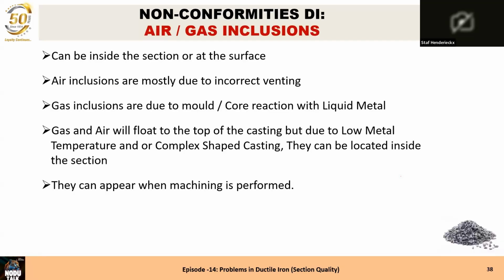Now we have air and gas inclusions. They can be inside the section or at the surface. Air inclusions are mostly due to incorrect venting, especially when they appear on top of the casting. Gas inclusions are due to the mold or the core, because some of the sand hardening systems will burn at around 500-600 degrees C temperature, and at that moment there will be gas. If the casting is not solidified at that moment, the gas can enter the metal.